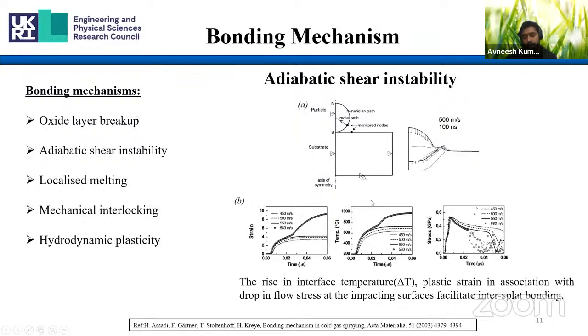These simulations were carried out by assuming that the substrate and the particle are the same material. If the particle and the substrate are different materials, then in some cases it was observed that this sudden rise in temperature reaches above the melting point, and some localized melting occurs at the interface, which helps in further bonding. For mechanical interlocking, researchers say that this jetting sometimes locks with the other particles' jets or the substrate jet, which forms mechanical interlocking and promotes the adhesion or cohesion of the particles. Then there is another theory, hydrodynamic plasticity, which says that for jetting, thermal softening is not necessary.